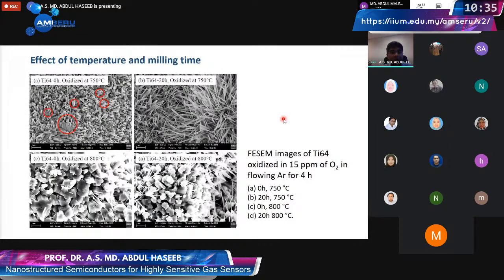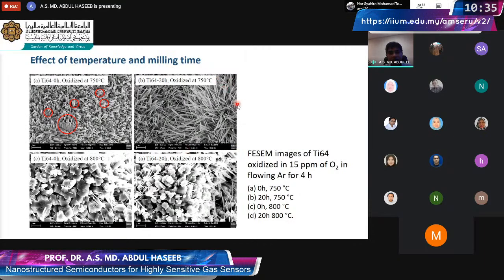The temperature also played a very important role. If you increase the temperature to something like 800 degrees, you see that you don't grow the nanowire. So we stuck to the condition of 750, where we get a decent quantity of nanowires on particles that were milled for 20 hours.